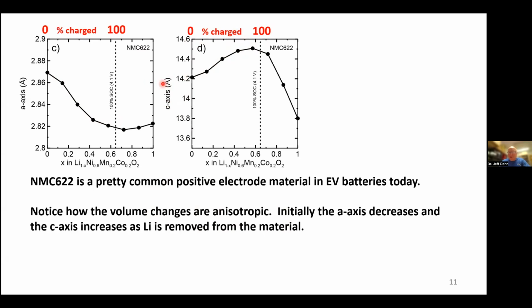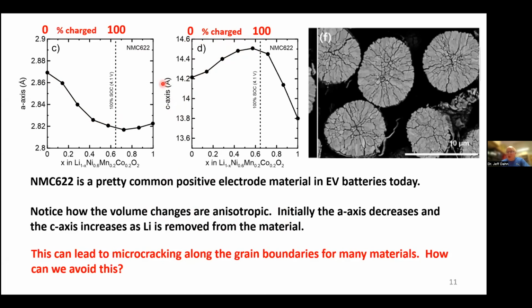And what this means is if you have a particle that's comprised of all these primary particles, as this expansion occurs over many charge-discharge cycles, it can lead to cracking of the particle along the boundaries between the primary crystallites, because some of them will have their A-axis this way, and the next particle will have their A-axis this way, and they'll be doing different things, and eventually that interface will break.